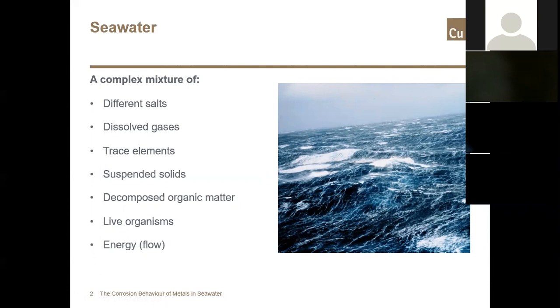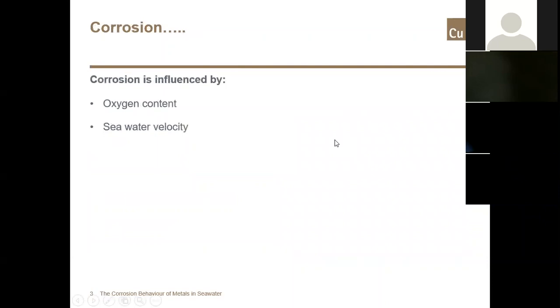Critically, the sea actually moves with great force, and the current or flow of the seawater can change dramatically, and this can have a large effect on corrosion. It's obviously not limited to natural movement and swells, and can also include the flow of water over the hull of a boat or a propeller, or even the flow of water inside a pipe or tube. Corrosion itself can be influenced by many factors within the seawater. The oxygen content can be hugely important to certain metals and alloys, as many of the metals will form oxide films on the exterior of the surface to provide a superior corrosion resistance. And the oxygen can be affected by water depth, seawater velocity, pollution, and marine organisms.